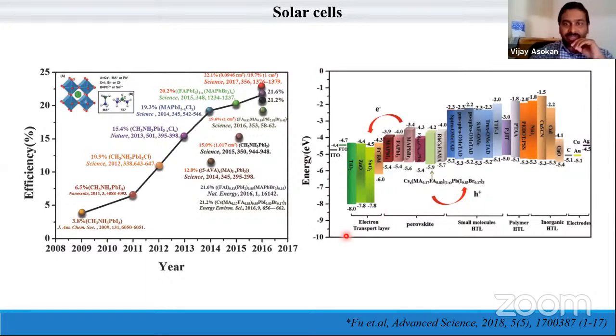Given here, you can play with different electron transport materials like titanium dioxide, zinc oxide or tin oxide. And for the perovskites, as shown here, you can vary different combinations or chemical ratios. Then there is the possibility of making different small molecule HTL, polymer HTL or inorganic HTL, because when we consider a wholly organic material like spiro-OMeTAD as an HTL, it gives some improved efficiency, but it is also very costly to procure, and it's not always easy to incorporate into the interface layers. So there are options for changing materials in terms of HTL.